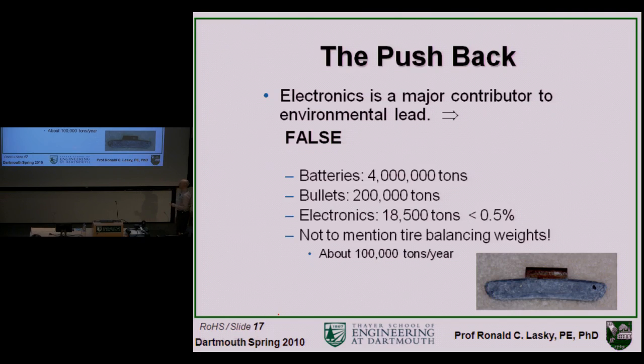This is kind of fun to me because myself and a graduate student some years ago did a little technical estimating on this. The tire weights are about 100,000 tons. So a lot of people were saying, why are we taking the lead out of solders for electronics? It's so critical when it's only such a small percent of what goes into the environment. And so there will be a lot of discussion at meetings about this. People actually did experiments where they would essentially grind up a circuit board, put some dirt in with it, pour some water in and let it sit for a year and then measure the water to see if they could measure any amount of lead, and it wasn't very much. And so people were really trying to push back against the European Union. And we'll talk a little later why this perspective is missing a key point.